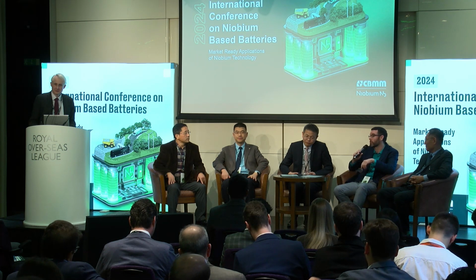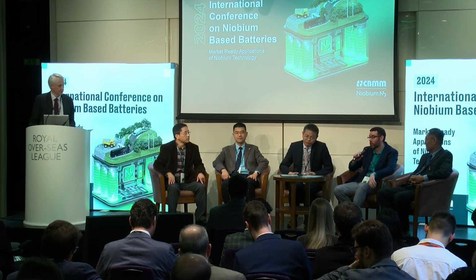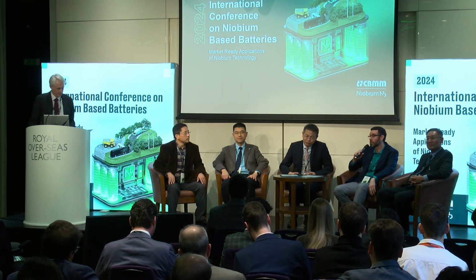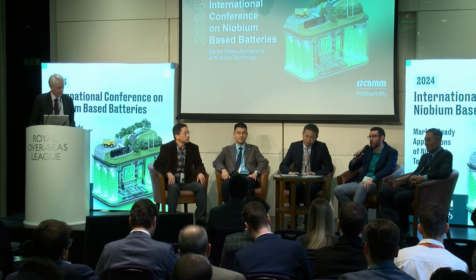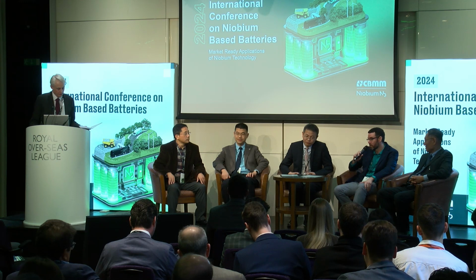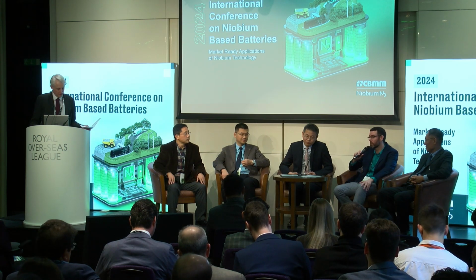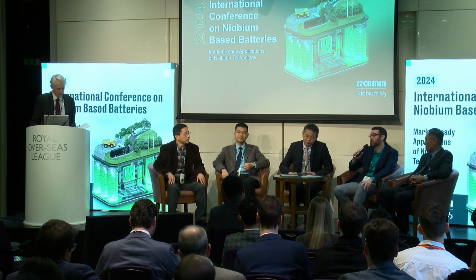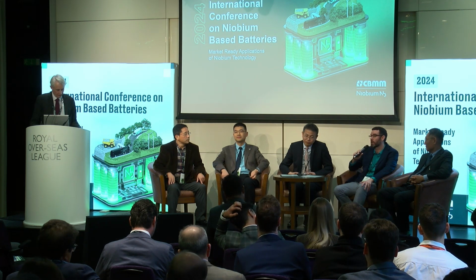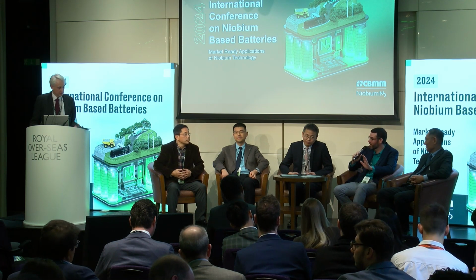The data I did show today was all about micron-sized niobium as a surface coating at 0.1, 0.2, 0.4 weight percent. I have also data that I'm not showing today purposefully for nano-sized niobium surface coatings with the same loading, and they did not perform as well as the micron size. So as today, very early days, micron for surface coating on NMC, at least NMC produced via an all dry zero waste process, is a little better than nano size.